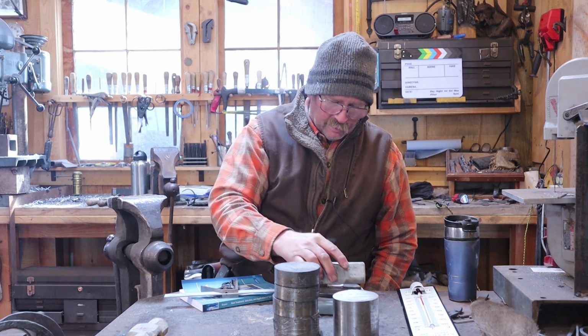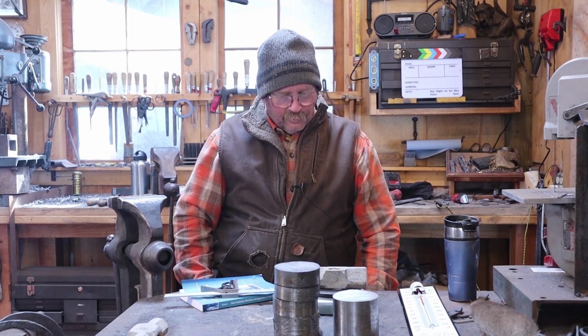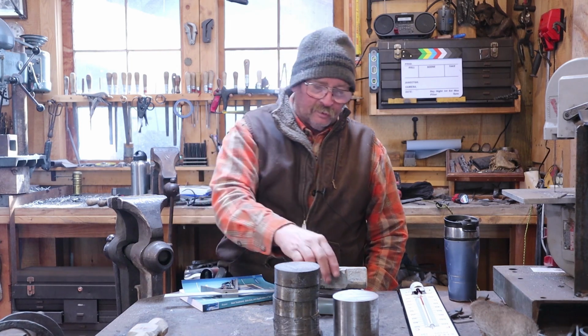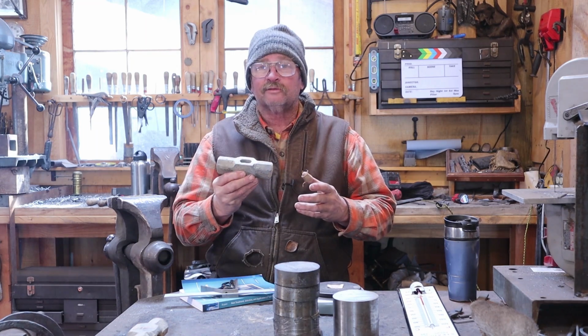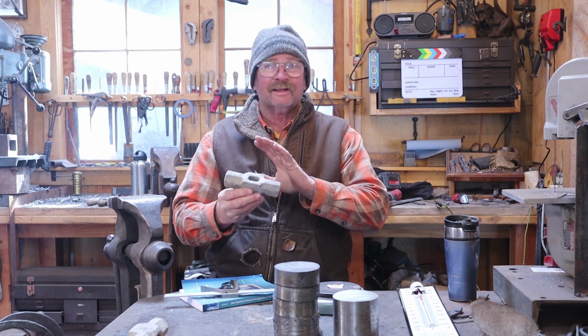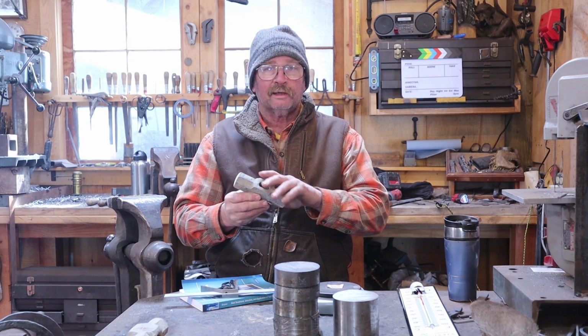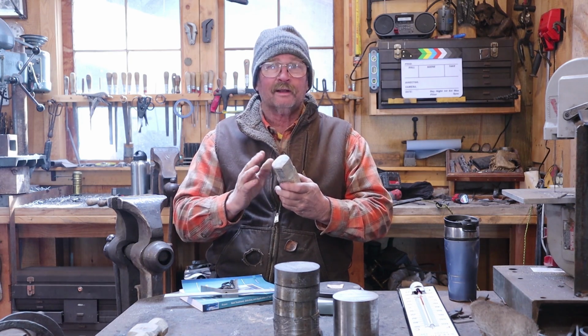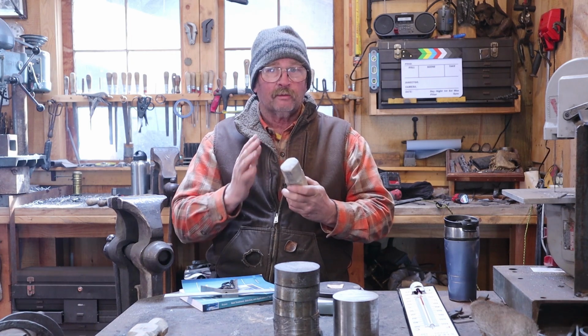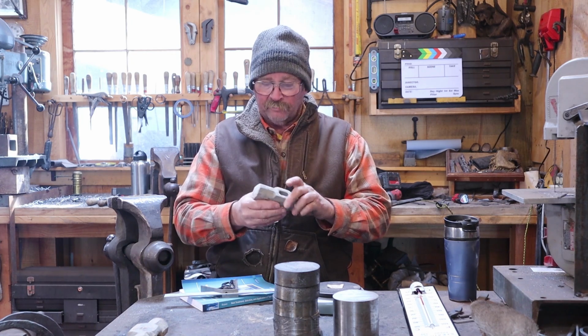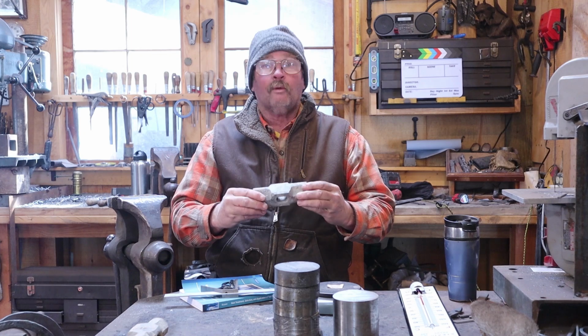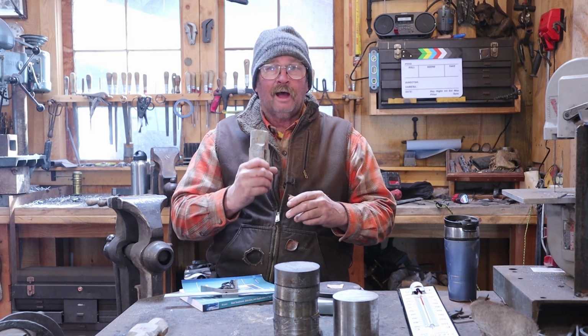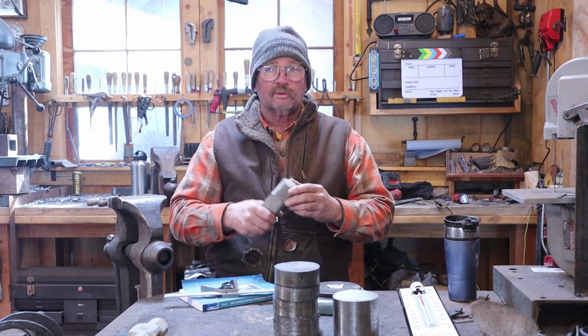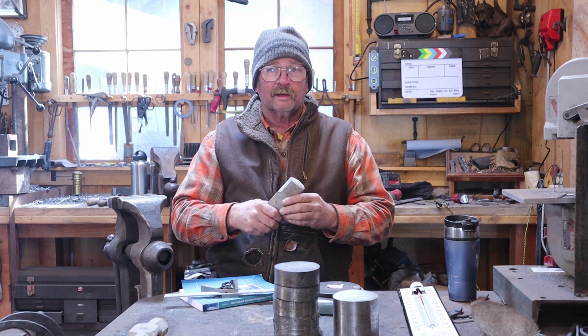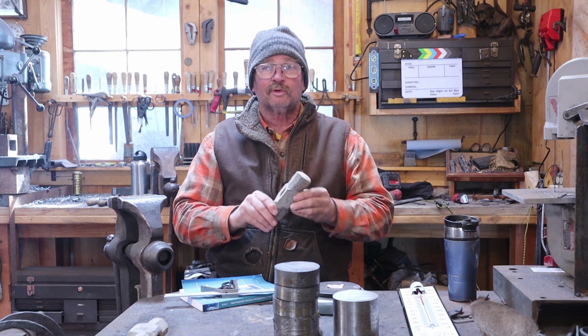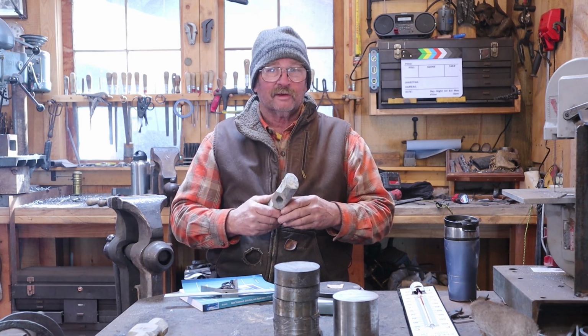Now we started with 3 pounds, 14 ounces of steel to make this hammer, and we now have, after forging, 3 pounds, 12.5 ounces. So right now we're still 4 ounces heavier than what I want this to be. That should be plenty of material to do some grinding. For that matter, I may have to grind a little bit more aggressively if I really want to get it down to exactly 3.5 pounds. So I'm going to go to the grinder. I don't think I'm going to show all the grinding, but I'll show a little bit of it because this is going to be about a half an hour of just creating sparks, and that doesn't make for a very exciting video.